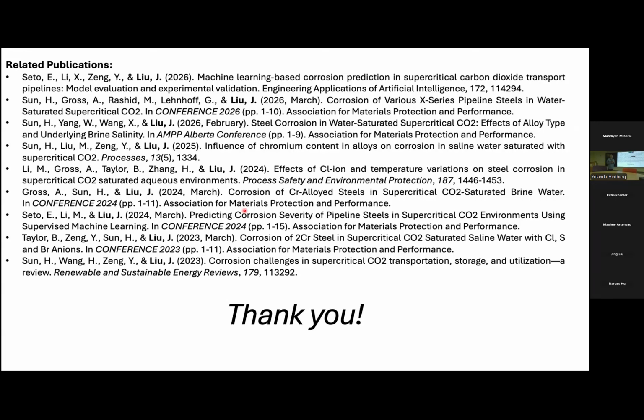Yes and no. The thing we noticed is the intermediate layer. The corrosion rate will be decided by it. Yes, you're right. It depends on what kind of intermediate layer we form. It might not be just chromium oxide. It might be because you eat lots of iron out first, and you left some other phase, for example Fe3C, iron carbide. Cementite. Yes. That makes sense. Then the chromium cannot be protective, but it still hinders the iron.